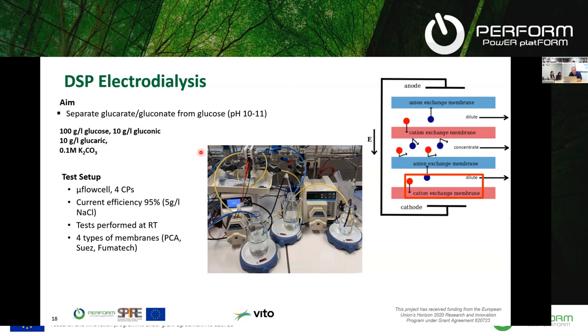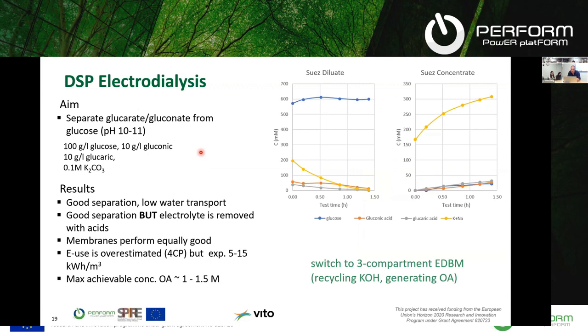It operates with a stack also consisting of alternating anion and cation exchange membranes. And tests were conducted in microflow cells, in this case, where we see that we can actually have a very good current efficiency for different types of membranes. And we have a very good separation of glucose and gluconic and glucaric acid. So the gluconic and glucaric acid are separated very well from the glucose. But in this case, with just conventional electrodialysis, also the electrolyte is removed. Electrolyte being alkaline, for example, potassium hydroxide.